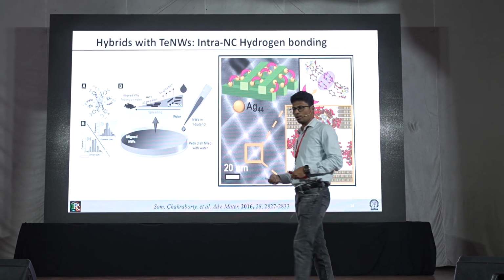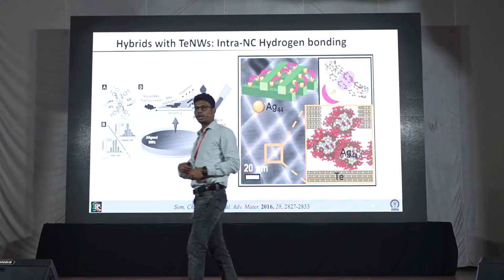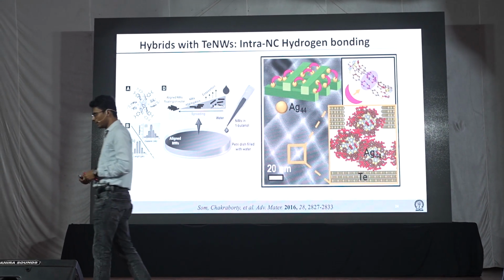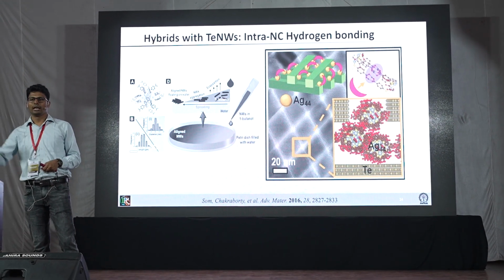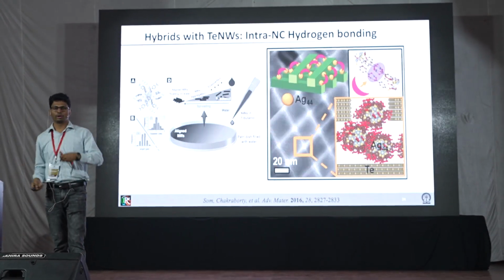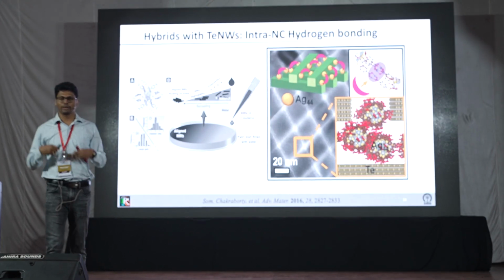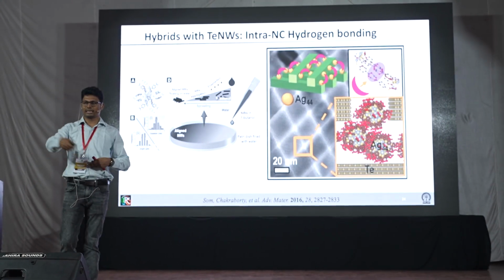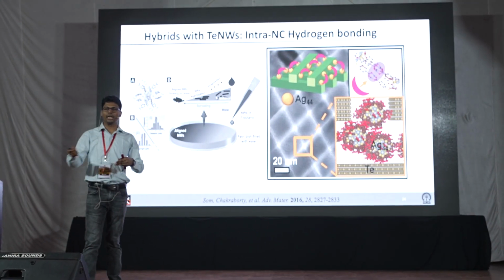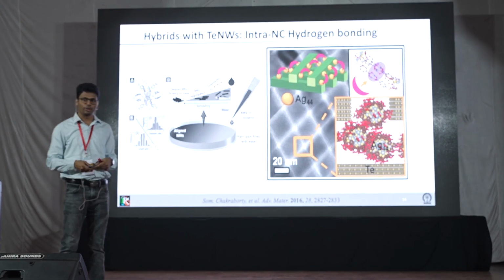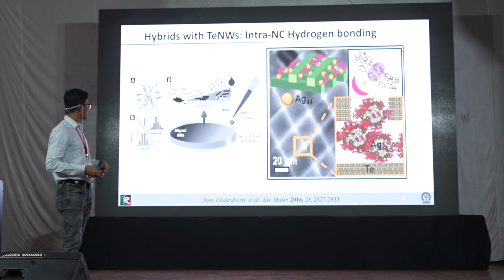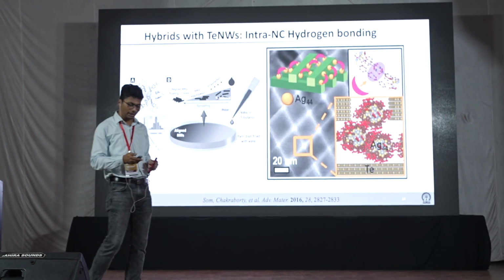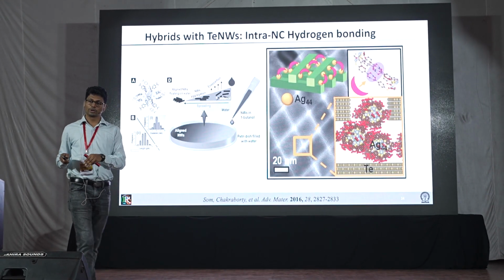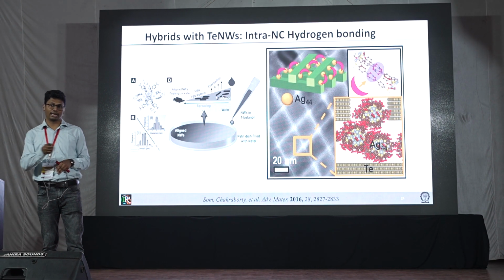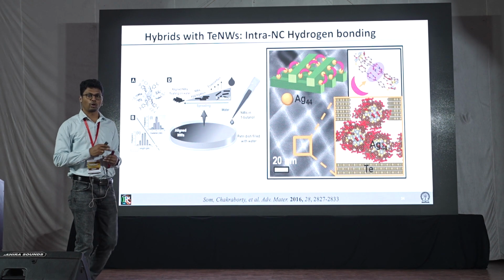But the major breakthrough came when we tried to assemble them, because one of my seniors, Anirvan, was working extensively on tellurium nanowires. And I saw he was doing the Langmuir-Blodgett self-assembly process for different aspects. Then I asked, when we incorporate clusters on tellurium nanowires, let us see if any change happens. So we saw, with the naked eye we could not see it, but when we put it in a microscope, we saw that tellurium nanowires, which are originally arranged as monolayers, are now crossed bilayers.